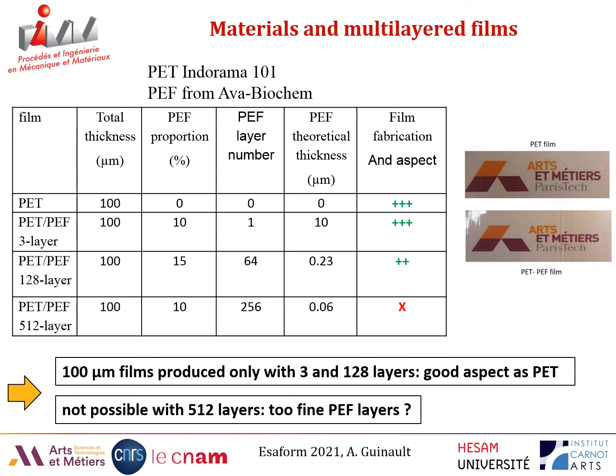So in this condition, we have obtained by extrusion good films, as you can see on the figure at right. The PET-PEF film looks like PET films, very transparent and of good quality, but it was not possible to produce the film with 512 layers, probably due to too fine PEF layers.